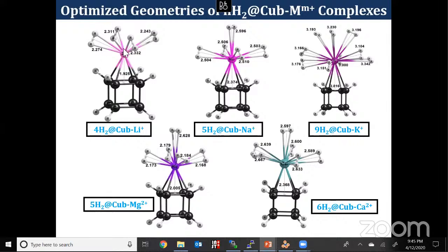One of the things we need to know is that when we have an anionic cluster, the hydrogen molecule forms a perpendicular type of interaction, that means an end-on interaction. But here, with the metal cation, hydrogen is forming a T-shaped complex. That means both hydrogens are trying to interact with the metal cation. For magnesium and calcium, it's the same scenario. When we move from magnesium to calcium, the van der Waals radius of the metal atom increases, so we can store more gas molecules over the metal atom.